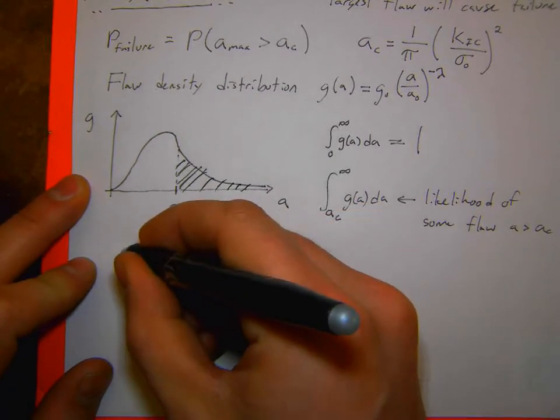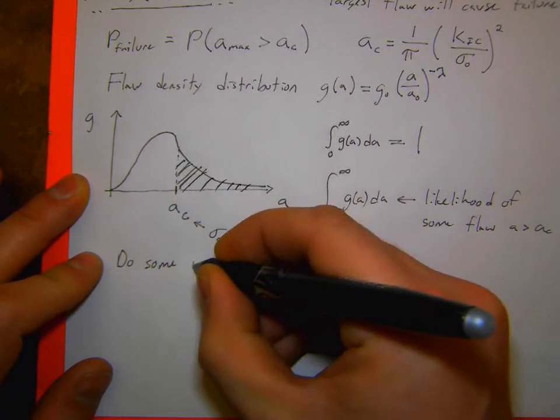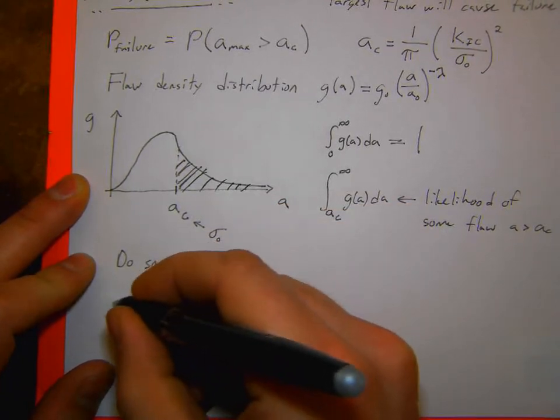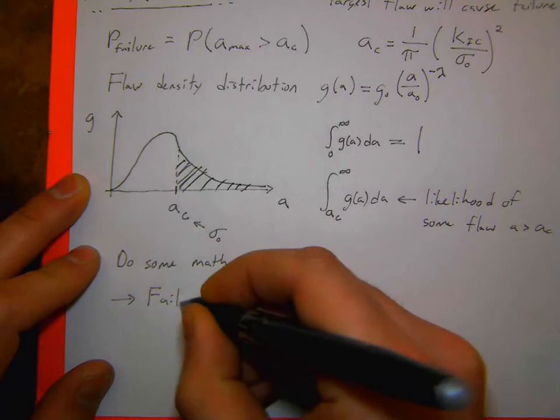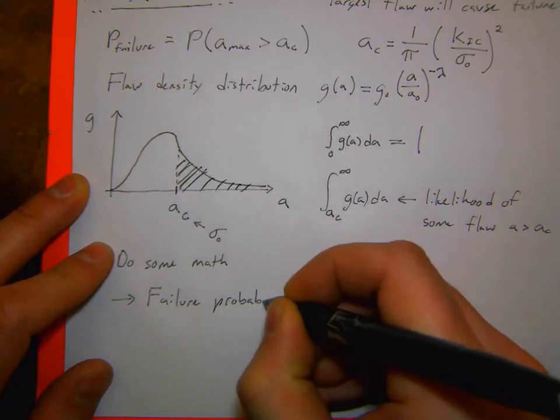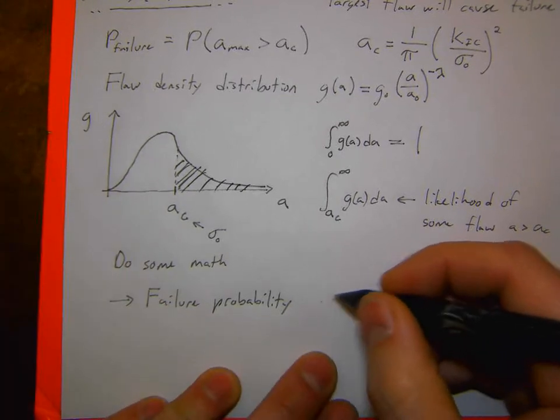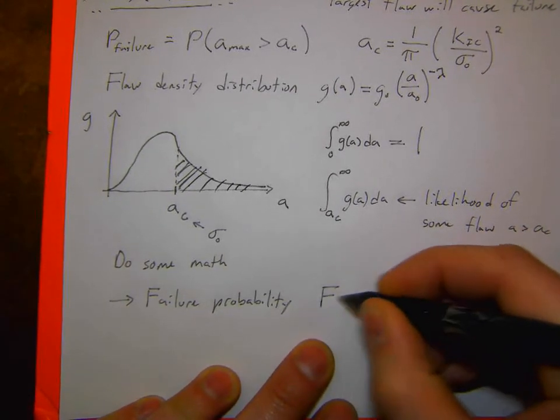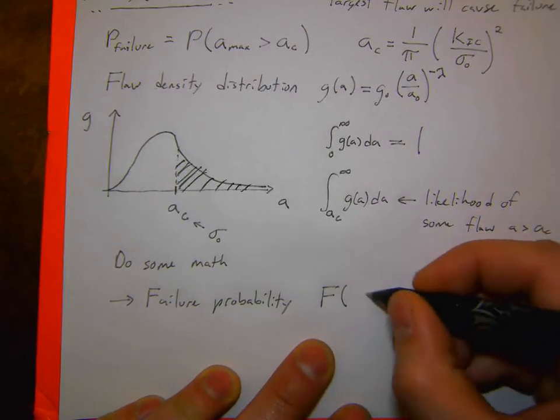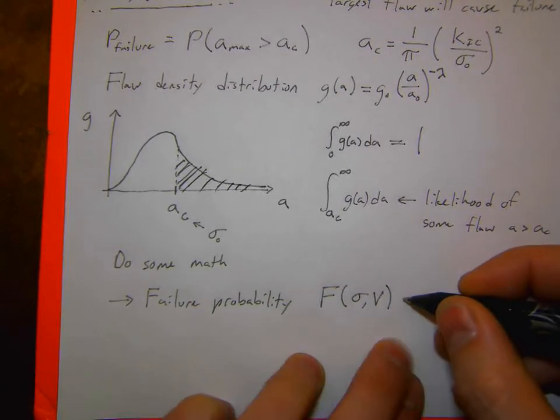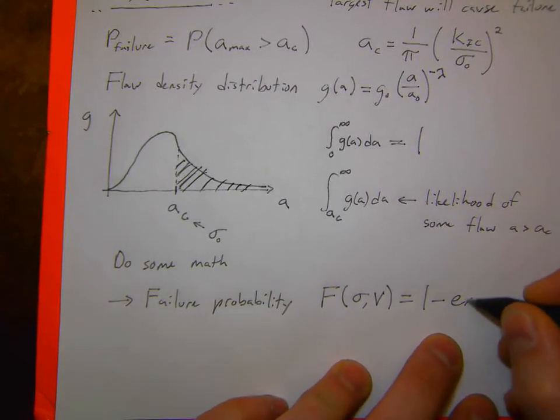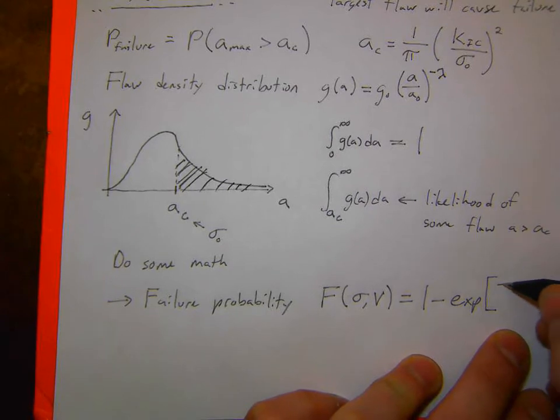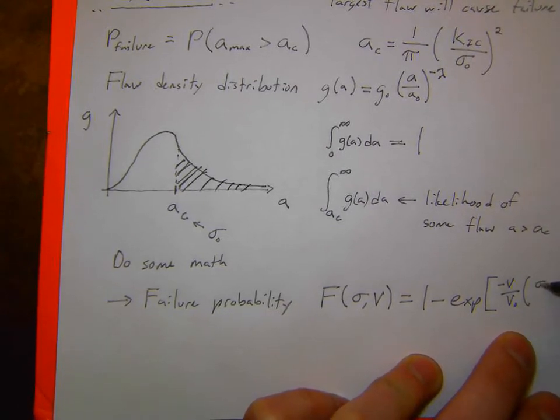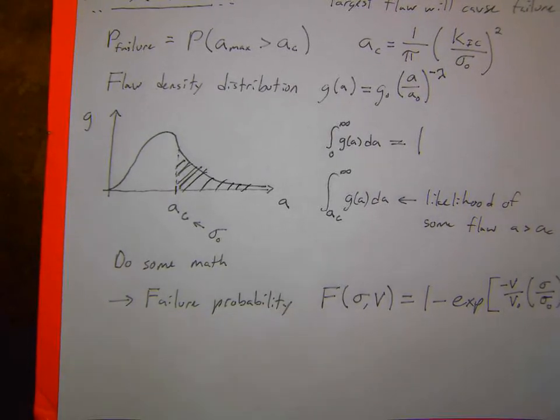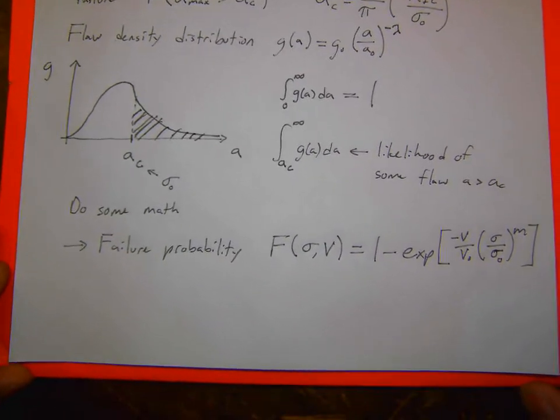So there's some math. And eventually what I end up with is the failure probability of a material, now of a brittle material, in terms of my stress and the volume of the part, is 1 minus exp of negative V over V naught, sigma over sigma naught to some exponent.